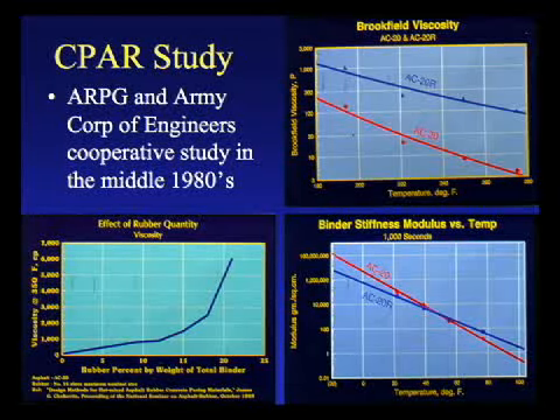If you follow this line, what you see is as you get up around 10%, there's a very slow slope, and as you get up to 15%, it even gets steeper. But look what happens around 18%. This is where we are, and that's why the product performs as well as it does. It's got an extremely large change in the viscosity of that original binder. That's why you can put so much binder in the mixes. It has a very high shear resistance. It performs very well in the field.